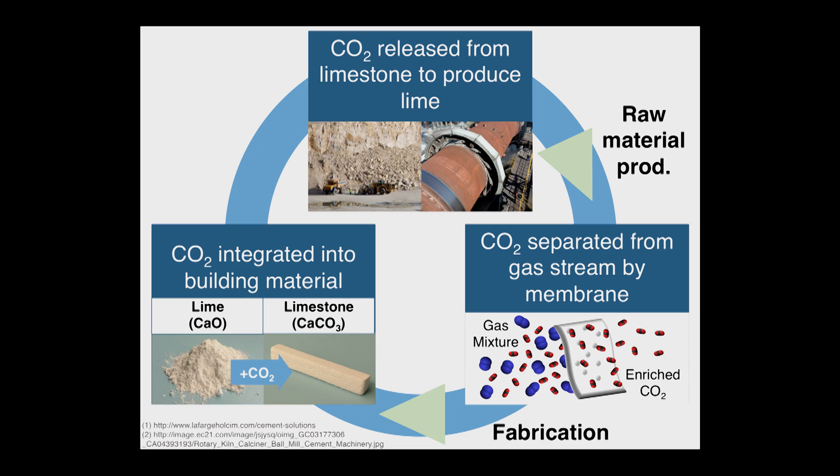We reuse the captured CO2 as a feed material in the next step. In order to fabricate our building elements, we mix lime into beams and columns using 3D printing, then expose it to CO2 under high pressure to form a final product composed of limestone. This increases its strength and also sequesters our CO2. We designed these pieces to be reusable, rapidly assemblable building elements, which can be disassembled to be reused later.